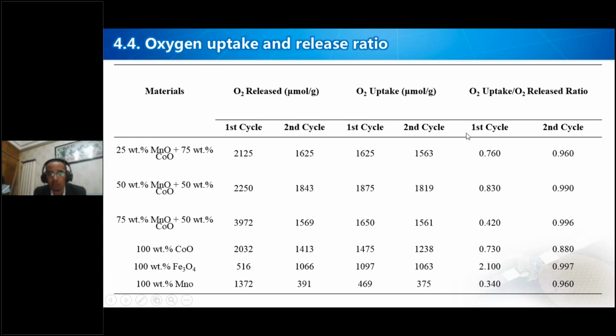50%, for example, in the first cycle is 0.76 in the 25-75 composition, 0.98 in the second cycle. When we think of 50%, 0.83 and 0.99 is okay. So when you compare all these six compositions, still the 50% weight manganese oxide and 50% cobalt oxide is in a good position for the absorption of oxygen, the uptake of oxygen, and the release of oxygen.